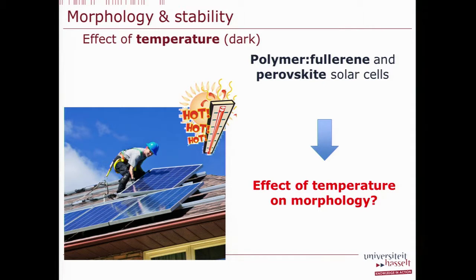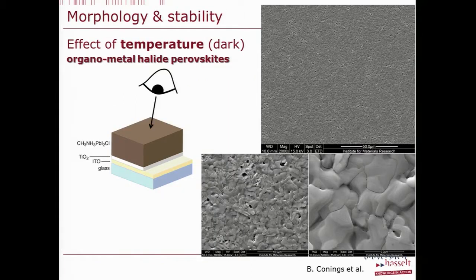Has temperature an effect on the morphology of polymer fullerene solar cells or perovskite solar cells? Just to start with the most recent one, what you see here is a solution-deposited film of perovskite. You can see here the morphology that we got. If you look on top with SEM, you see these grains. It's not very flat, but this is the kind of morphology. Also there, since the efficiencies are quite high, people are putting in a lot of effort to understand how the degradation is occurring.